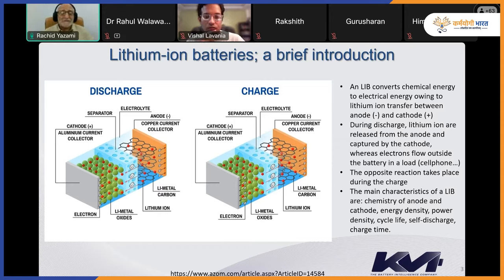But the interesting thing is that the total amount of lithium in the battery is constant, especially in the electrolyte. If there is no side reaction, as soon as one lithium ion is put inside the electrolyte, another lithium ion is consumed on either the anode or the cathode side. So the concentration of lithium in the electrolyte is constant; it doesn't change. Okay, so this is how it works, and the charge and discharge process can be repeated many hundreds of times. According to the materials used and the conditions of charge and discharge, more than 1,000 or 2,000 cycles can be achieved using this lithium ion battery.